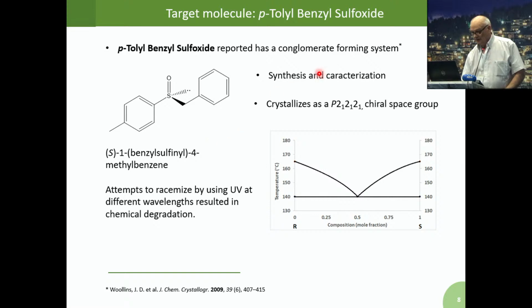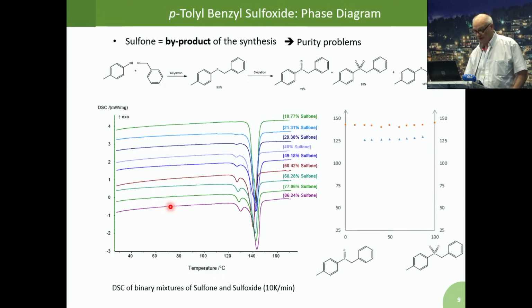First, as it is a conglomerate, and this was published then, we tried to attempt racemization, because if we have racemization and this conglomerate, so we have the two conditions fulfilled, and then we could deracemize. But unfortunately, by using UV and at different wavelengths, different energy, and so on, we got much more chemical degradation than racemization. So we could not use that. So I will depict how we performed the preferential crystallization.